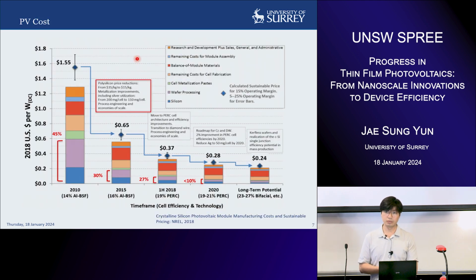So what has driven the cost reduction of wafer, and made thin film step out of the market? I think the main driver is related to the cost of the wafer. Back in 2010, with aluminum back surface field solar cells, the cost of wafer processing and silicon was around 45%. You can see it gradually reduces, and nowadays with PERC it's actually less than 10%. So there has been a great reduction in the cost of dealing with silicon, including the low material cost of the silicon. It has gone very cheap, and now the efficiency has gone up, which makes it a very competitive PV technology.